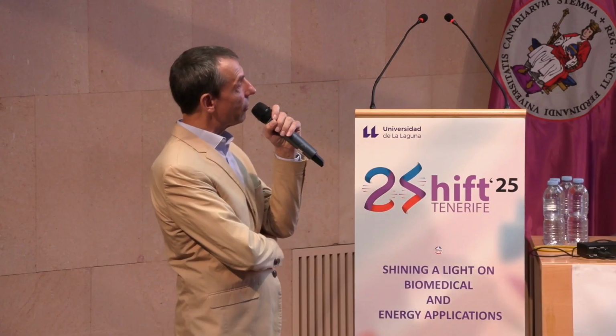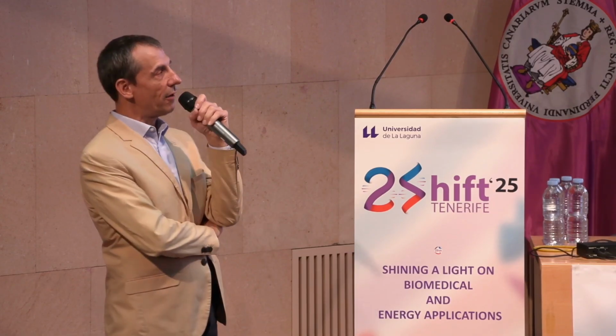Then you have the question of relaxation. So here we are in a relatively good situation, right? Because we had zero magnetic field, the direct process does not happen. And then you have the hyperfine interactions, which are not too large, so this also gives a small contribution to the spin-lattice relaxation. And for the two-phonon relaxation, Raman and Orbach, this is very small because we are at 50 milliK. At these temperatures, you essentially have no phonon excitation, which is really important. And so this is why you have such long spin relaxation times.